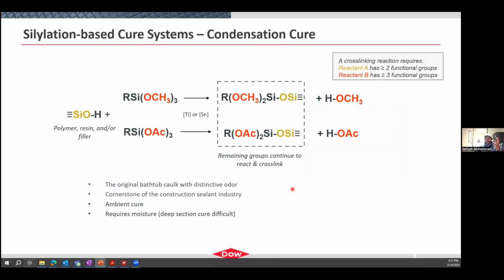So again, if we think about, we want to add in something that can branch PDMS. So we will often have a reactant in there, which is trifunctional at least. Sometimes we use tetrafunctional, but it needs to have 3 spaces for it to bind PDMS. If it only has 2 spaces, then what you might end up doing is actually just growing a super long chain of PDMS, right? So you don't want that. You want some cross-linking. You want networks where it has a T.